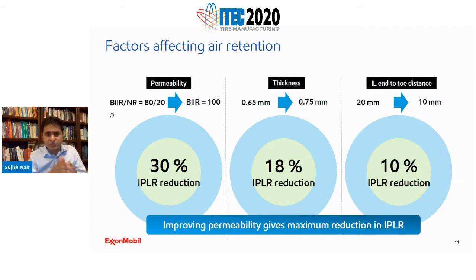The first one is material permeability. The lower the permeability of the rubber you use, the better your air retention is going to be. For example, we have done a couple of different experiments with multiple different compositions. Let's say you use a blend of bromobutyl and natural rubber, an 80-20 blend, which is commonly used in the industry, versus going towards a 100% bromobutyl inner liner. We see an inflation pressure loss reduction of